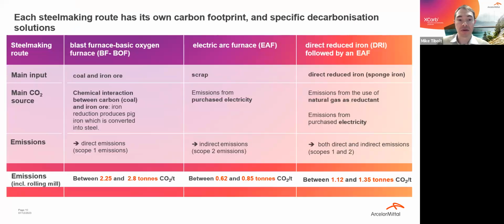So we see here the main production lines of steel that are currently used, especially on the left and in the middle column. On the left column, we have the well-known production line, the blast furnace with BOF. So here we take coal and iron ore. Iron ore is reduced by coal in the blast furnace to produce pig iron, and then later processed to steel. The main CO2 source is coming from this chemical interaction between carbon and iron ore. And if we also include the emissions from the rolling mill to produce a final product, we see that we have an average between 2.25 and 2.8 tons of CO2 per ton of steel produced.